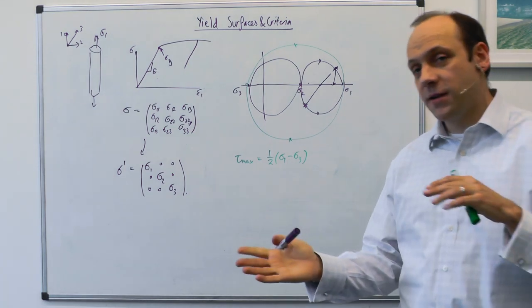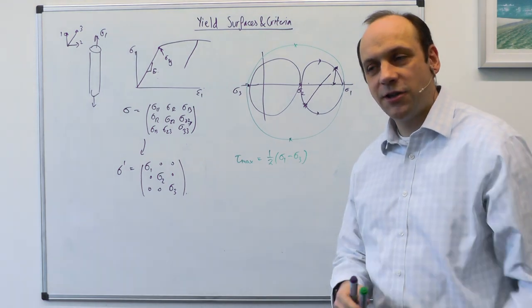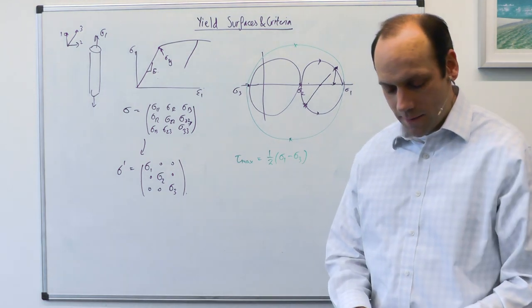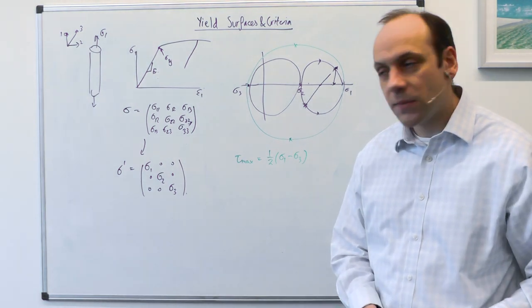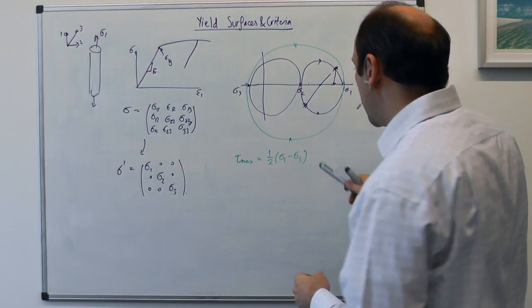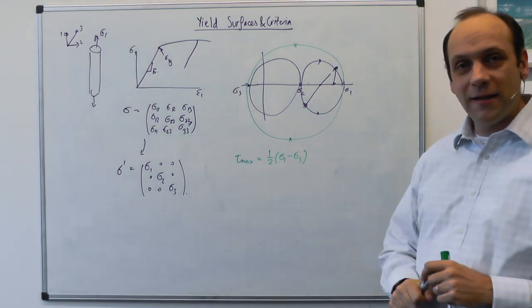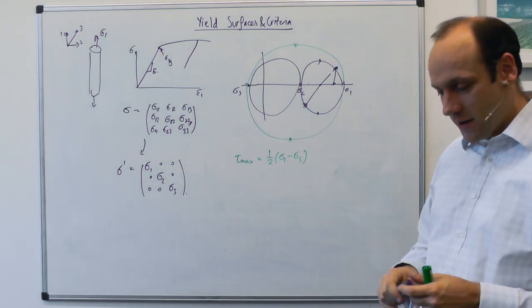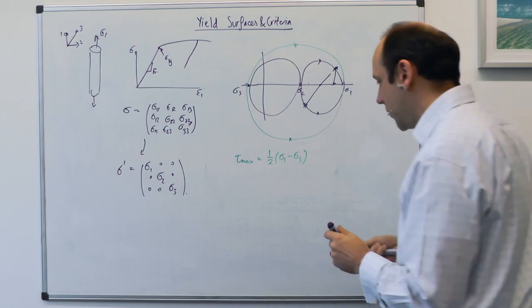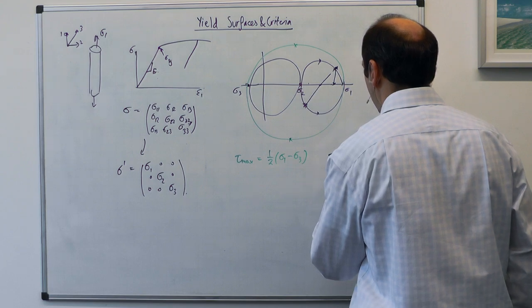And we've said previously with dislocations that plasticity is a shear process. It changes the shape of the body, but not its volume, and that's something that shear does. So if you ignore crystallography, this is a good criterion for finding yielding, and that's called the Tresca criterion.